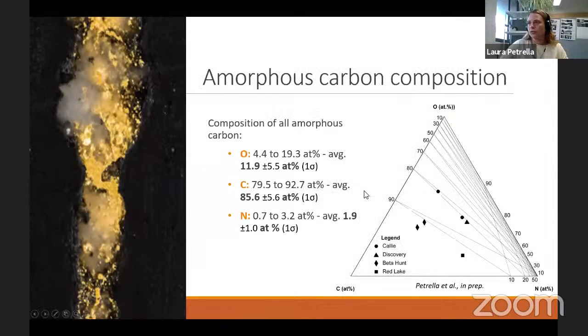We have been able to analyze the amorphous carbon phase, and it is obviously mostly composed of carbon, but also contains a significant amount of oxygen and nitrogen. That is an interesting observation because this is a composition that approaches the carbonic-rich fluid inclusions in orogenic deposits. These carbonic-rich fluid inclusions are usually composed of CO2, CH4, and N2.